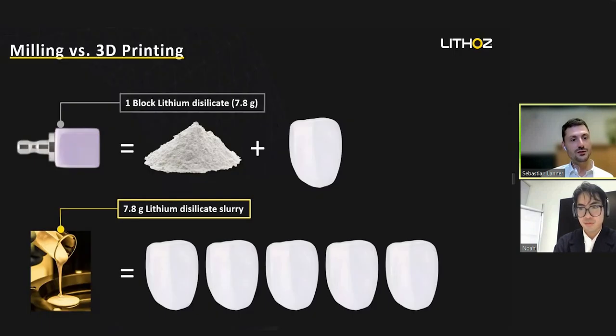When you see here compared to milling, when we take a block of lithium disilicate with an amount around 7.8 grams, you can go for one indication, one restoration. And the most of it is basically waste. And if you use the same amount of material and go, for example, for one of those ultra thin veneers, you can go up to 5 veneers with just that amount of material. And this allows us to use almost every material that's in the vat.